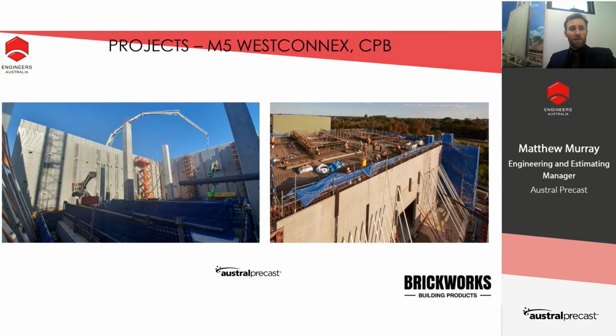Some other projects here, we have the M5 WestConnex. This is an exhaust tunnel building at Arncliffe. One of the key things with this structure is that it uses double wall as a deep beam wall for 2 sides of this structure, and also has integrated buttress columns. Essentially here we have 12-meter high walls with the outer shell protruding 1.5 meters above the panel, and that allowed the installation of some large precast beams to tie into the panels.